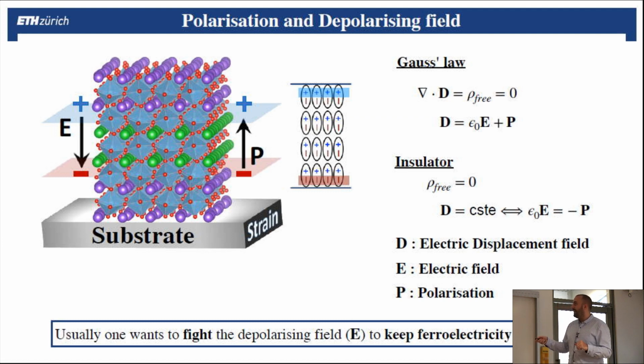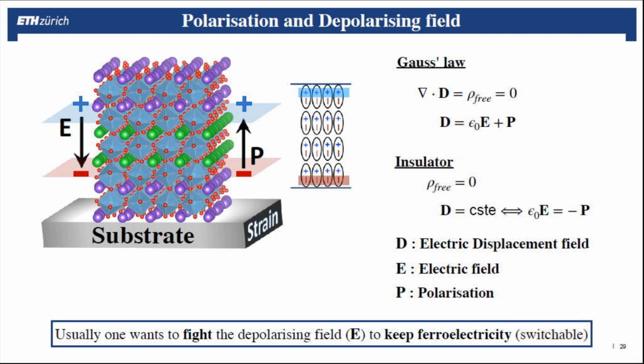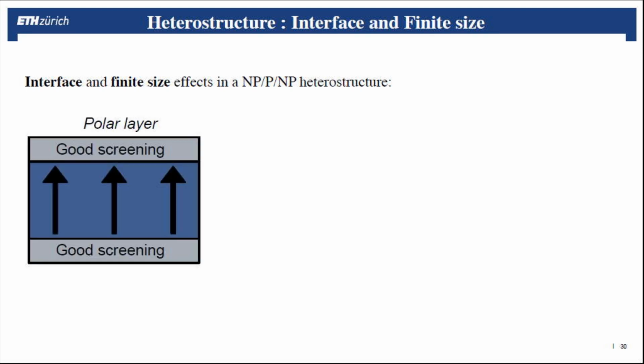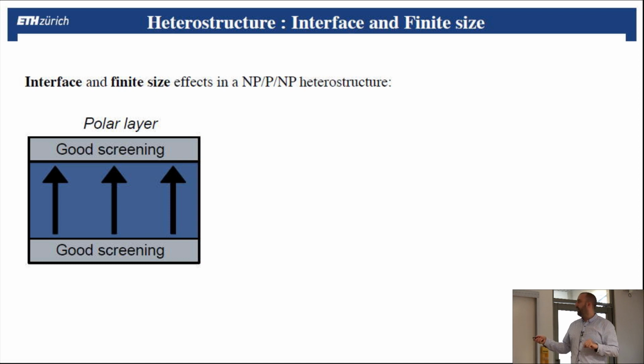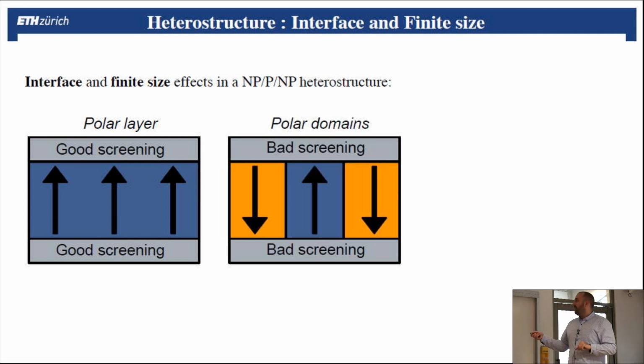And usually people want to fight against this depolarizing field because, as I told you before, we want to have ferroelectric materials and to be able to switch them by applying electric field. But let's go in a different direction here. So imagine that you have a non-polar material, a polar material, and again a non-polar material, as I showed you in the heterostructure just before. If the non-polar material has a good screening, imagine it's a perfect metal, it can move charges around and come in the interface and screen the charges, and this polar material will stay polar and stay happy.